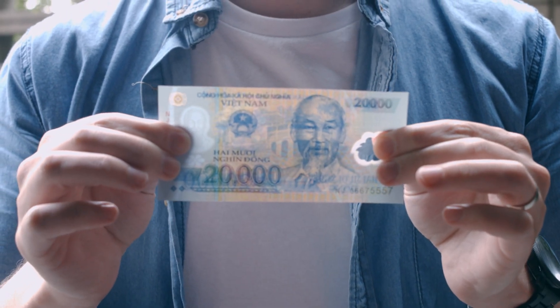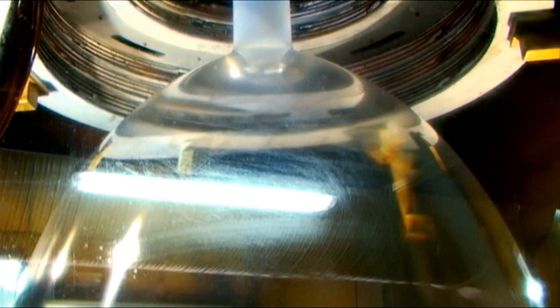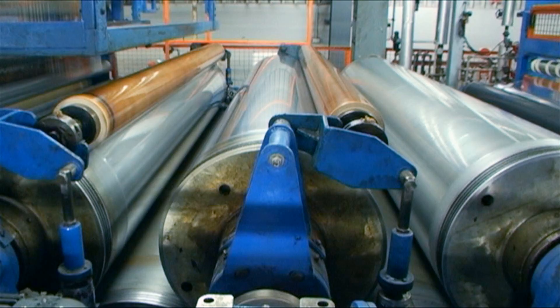So how do they make it? The process starts in a highly secure location at Inovia Films, who manufacture the base film called Clarity C. It all begins with clear pellets of polymer that are fed into the top of a very tall machine and melted. As the liquid polymer flows downwards, the film is formed by creating the world's largest bubble — that's four stories high. There's gravity on the outside of the bubble and air pressure on the inside. The liquid polymer at the top of the bubble is stretched into a delicate but highly robust material manufactured to a thickness made exclusively for banknotes. As it cools towards the bottom of the bubble, Clarity C becomes a solid film structure that's rolled into large reels.